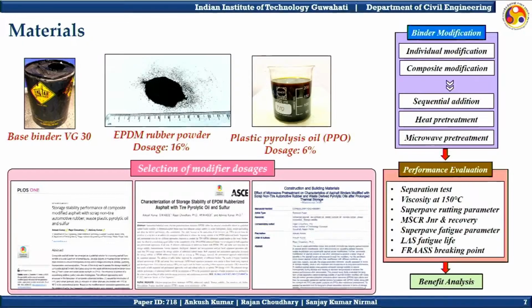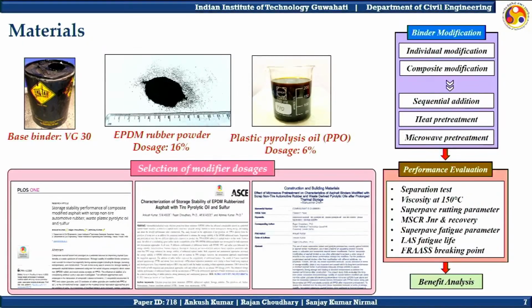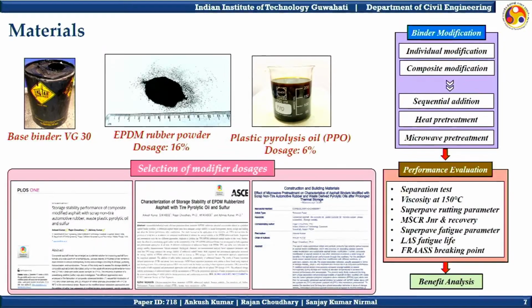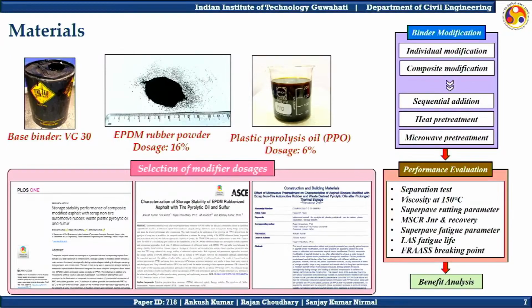Those vapors are condensed to obtain the pyrolysis oil, while the uncondensed pyrolysis gas or vapor are used to run the pyrolysis reactor, and the solid carbonaceous plastic pyrolysis char is also generated. So coming to the materials used for the modification in this study, a viscosity grade 30 base binder was used, and the EPDM rubber granules or powder, less than 300 microns in size, was used at a dose of 16%, and the plastic pyrolysis oil was used at a 6% dose. These doses were selected based on our past research studies.